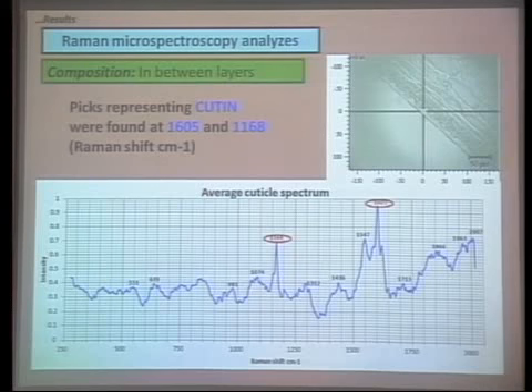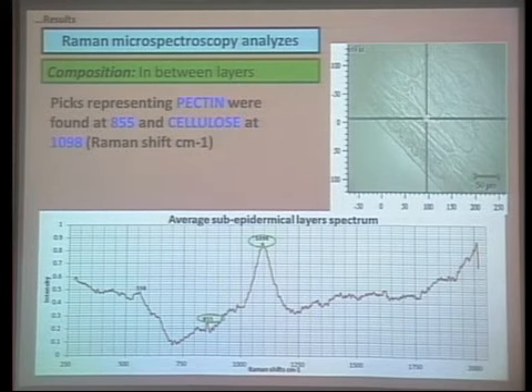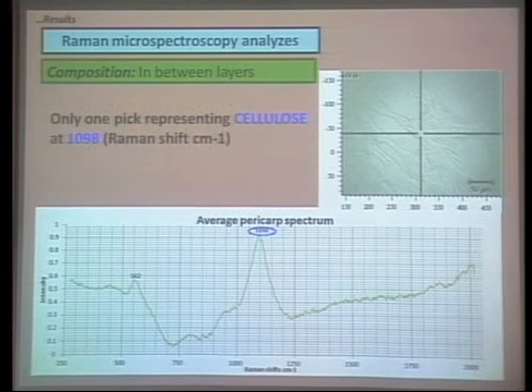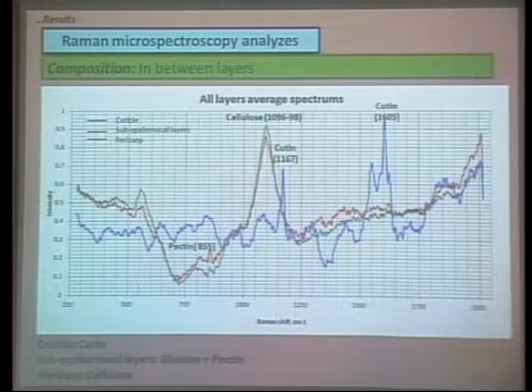So in the cuticle, we had two major peaks, and then we went to the Raman database, and we saw that these two peaks are representing cutin. Then we went to the subepidermical layer, and we see that we got pectin here and cellulose here. And then from here we went to the pericarp, and in the pericarp we saw only cellulose, no more pectin. And then we averaged them all without making the differences between 1.0 and 1.5 and 4.0, because we didn't see any differences in intensity here. So we saw differences in composition in between the layers, but not in between the treatments.